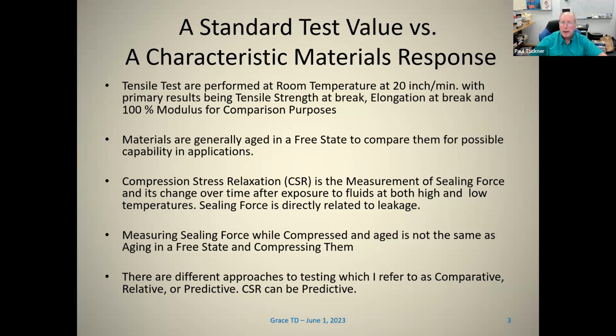Compression stress relaxation is a measurement of sealing force and its change over time after exposure to fluids at both high and low temperatures. Sealing force is directly related to leakage. Measuring sealing force while compressed and aged is not the same as aging a CSR test specimen in a free state and compressing them afterward. They're 2 different things.